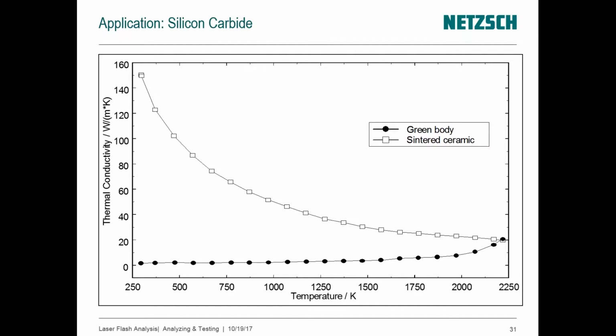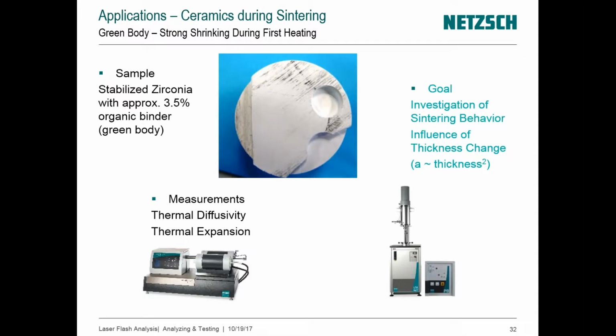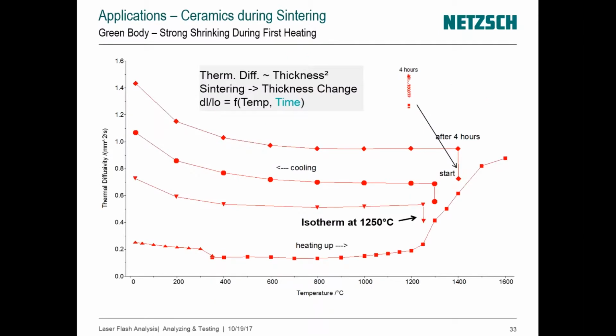And that's what we'll be doing here. Again, you see, we'll combine measurement obtained with a dilatometer with measurement obtained with a laser flash, with an LFA, the 427 in that case, and calculate the true diffusivity as a result of the sintering. So that's what you see on the graph here. Let's look first at the data represented here with a square, the red squares. That would be what would happen if we were just taking the green body and heating it up all the way to maximum temperature. So you will see at some point the sintering occurs suddenly. I mean, it occurs above 1,200 degrees Celsius, but you see the effect right here.